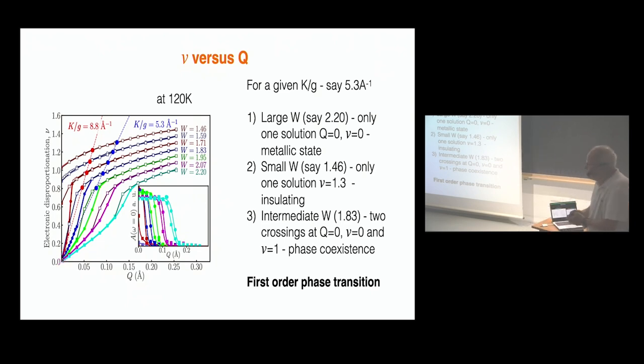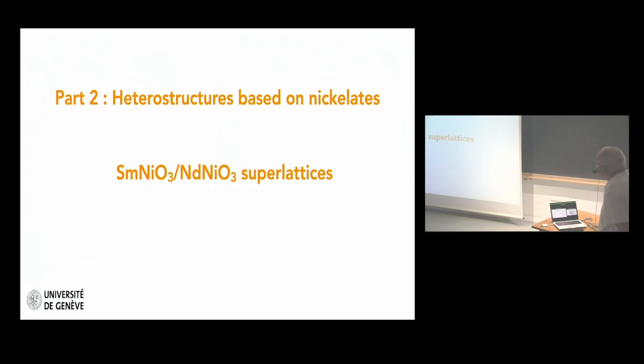So the system is metallic. If you take a small W, 1.46, there is only one solution for a finite Q, finite nu or n. This is the insulating state. But what you find is that for an intermediate bandwidth, like this 1.83, you find two solutions to this equation, and so it's telling you that you have phase separation. So this result is telling us that the transition is first order. And this is in line with what I mentioned before. Okay, with this, let me now switch to the second part of the talk where I wanted to show you some of the recent, yes, Claude?